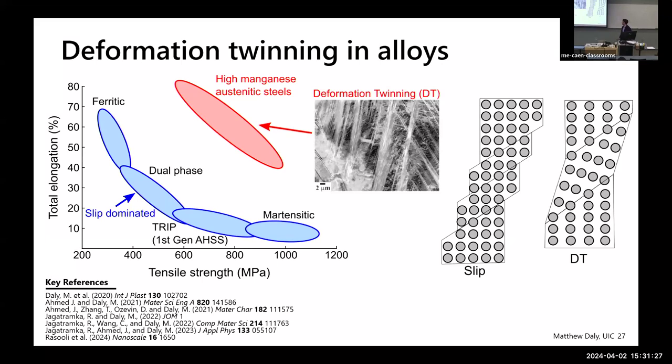Whereas deformation twinning is completely coordinated. Deformation twins only nucleate and grow by a coordinated nucleation and progression of dislocations in a specific sequence across a sample. And because of the nitty-gritty of this sequencing, what you're left with when these twinning partials leave this system is a unit cell that has a rotated lattice. And you can see that across these deformation twin boundaries, which I'm showing here, the unit cell has been completely rotated in symmetry.